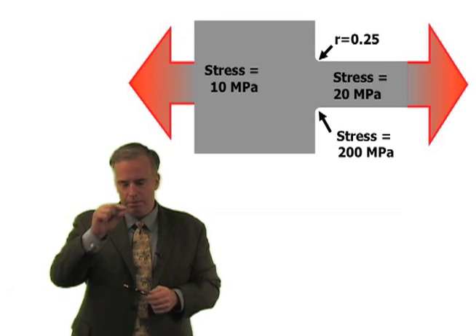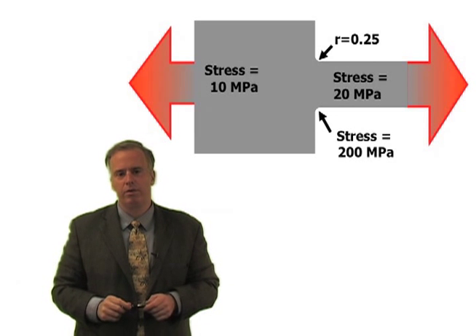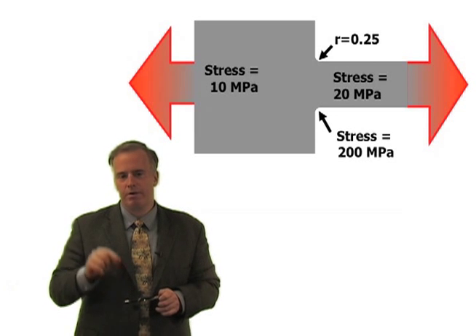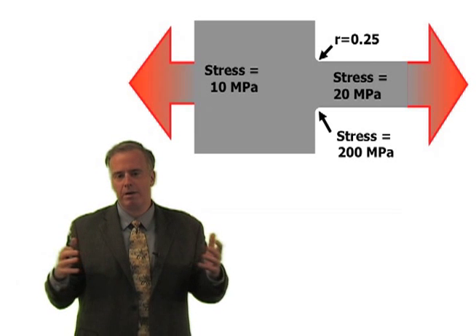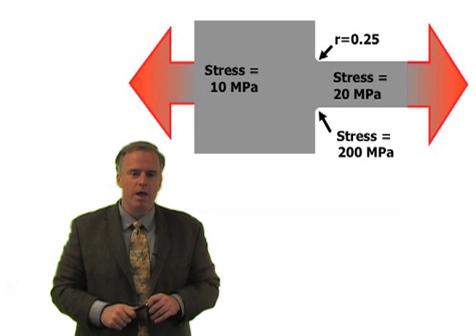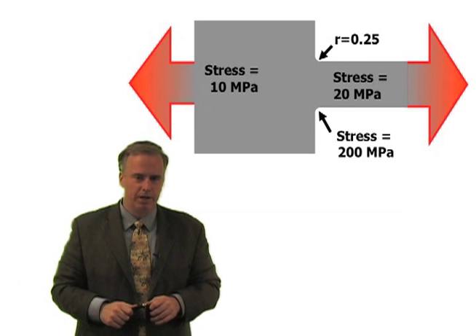If we take that same part and we pull on it, but that part has a very small corner radius, then the stress at that very small corner radius is going to get magnified and is going to be much more likely to crack.